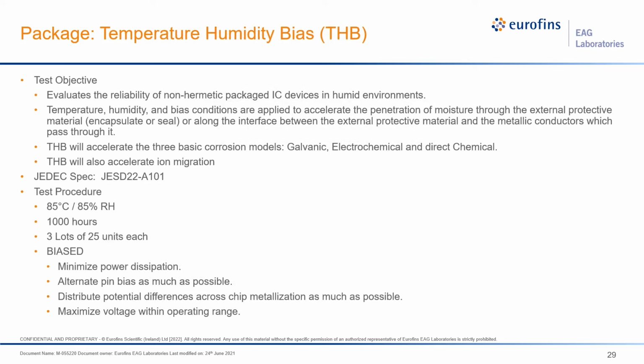Temperature humidity bias, also known as 85/85. This test is another bias test. It is extremely similar to the biased HAST, and it tries to promote the same type of failure mechanisms. The major difference is that the temperature humidity bias test is much longer. It's done for 1,000 hours and it's performed at 85C and 85% relative humidity. It has largely been replaced by biased HAST because of the much longer duration of this test. Most people prefer the biased HAST. For some devices that are high power, the biased HAST may not be suitable and they may be more suitable for the THB. You may refer to the JEDEC spec 22-A101 for more details on temperature humidity bias testing.